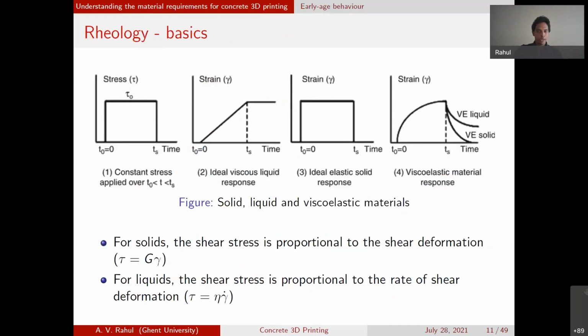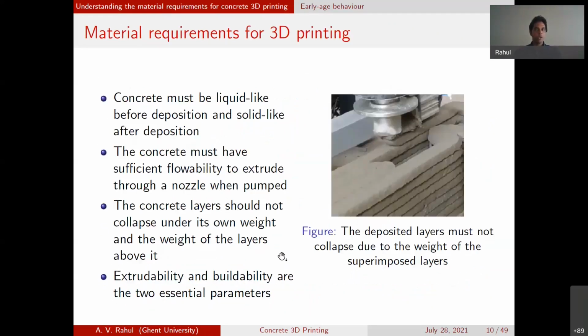So now going back to this question of how we utilize concrete in 3D printing, the idea is to design concrete with very high yield stress. If you look at conventional concrete, they usually have a yield stress in the range of 100 or 200 Pascal, a relatively low value as compared to 3D printable concrete. A 3D printable concrete would have something closer to 2000 Pascals.